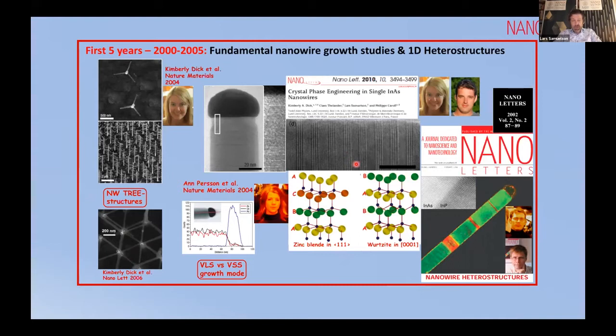Also a lot of effort on trying to understand and control structural properties. Maybe you can't see the detail, but this is a superlattice, all indium arsenide. These segments are cubic zinc blende structures of indium arsenide, and these are hexagonal wurtzite structures. You can see 8 monolayers of each of them, making an interesting superlattice combining these structures with interesting transport and optical properties.